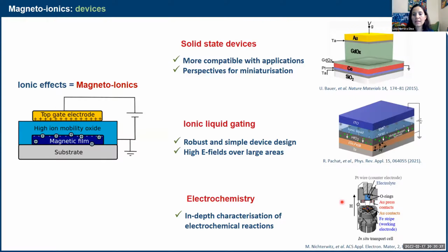What is important to know is that an electrolyte is not an ionic liquid. An electrolyte is actually a solution of ions that actively participate in the magnetoionic process. So you have, for example, iron oxide that is reduced into iron, and that oxygen goes back into the electrolyte. Then you can also have ions that get deposited onto your layer because of the changes in the voltage. So the electrolyte is actually very active in the ionic process. This is not the case with the ionic liquid. The ionic liquid is just a tool to generate an electric field. It does not interact chemically with your layer. So that's a fundamental difference.